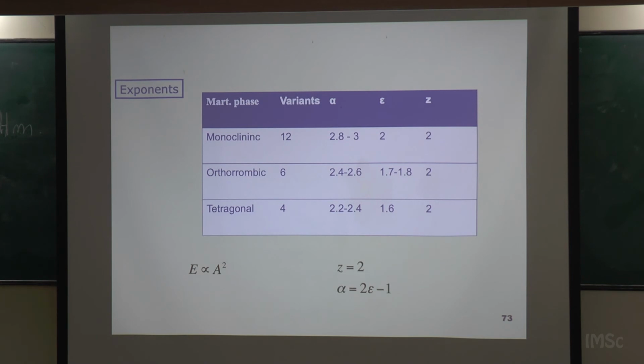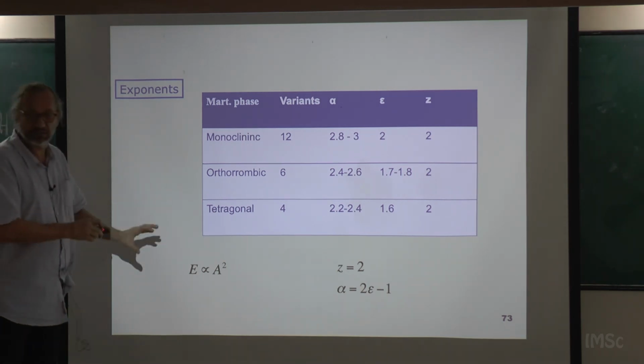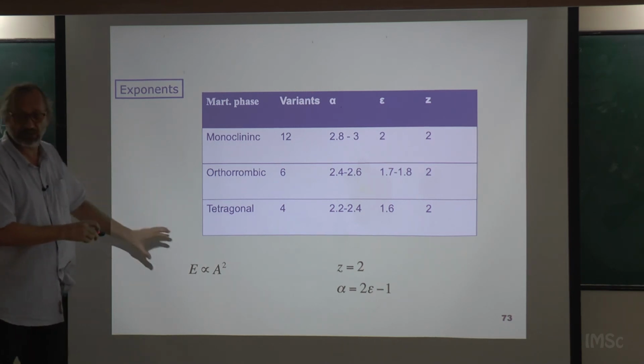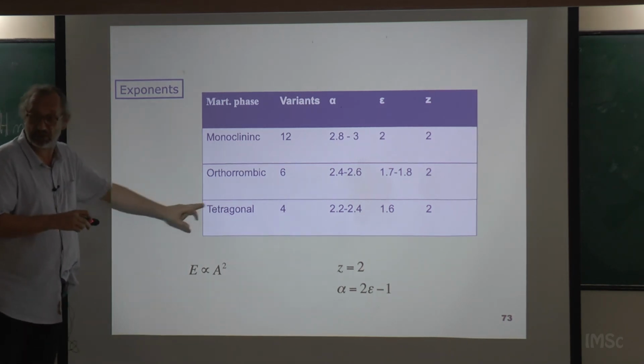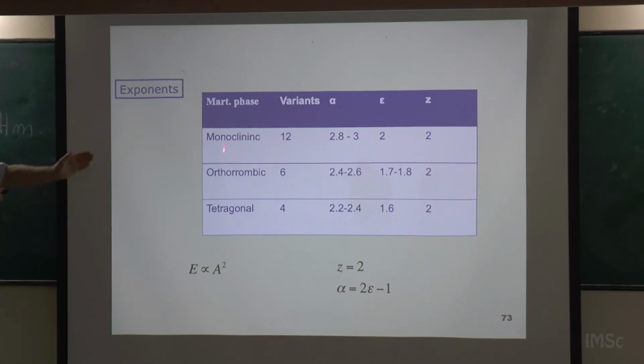It turns out that when you analyze many structural phase transitions, in this case, we studied phase transitions starting in the cubic phase and going to different structures. You can go from cubic to monoclinic, from cubic to orthorhombic, and from cubic to tetragonal. This is the iron palladium I was showing, and different alloys in each case. And one can check that